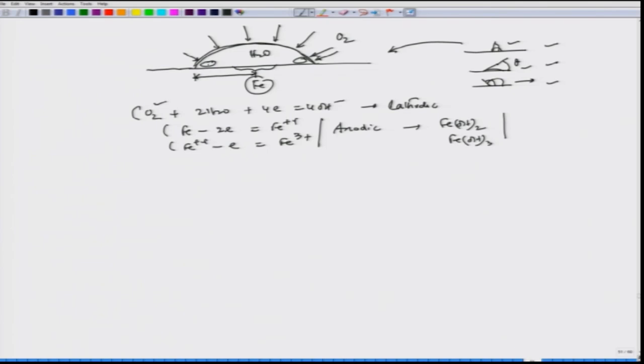So, oxygen content in this section remains almost the same from the starting of the reaction as well as during continuation of the reaction. But at this zone, the oxygen is consumed, because since it is a diffusion process, that oxygen has to diffuse through this layer and go to this. Even though it is a small droplet, still it takes time for the oxygen to reach that particular section. So, now here we have oxygen deficiency, and here we have almost similar oxygen.